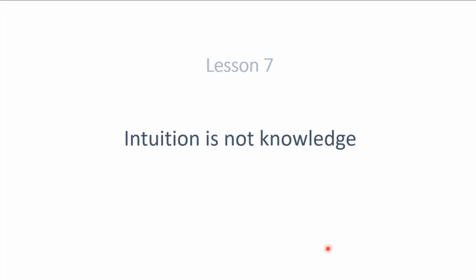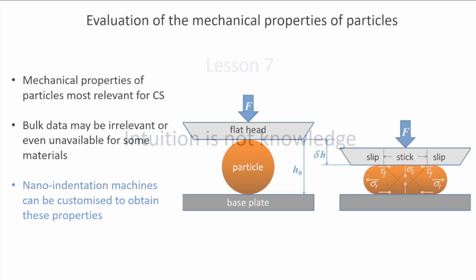So the first thing that you need to know about the particle, apart from the thermophysical properties, is the mechanical property. But how can you extract something like UTS from a tiny micron-sized particle? So what we did also at Helmut-Schmidt University was to use a nanoindenter, but modify it. So instead of indenting anything, we replaced the indenter with a flat head, and then we squeeze the particle, and then measure the load versus displacement in order to extract those constitutive properties.